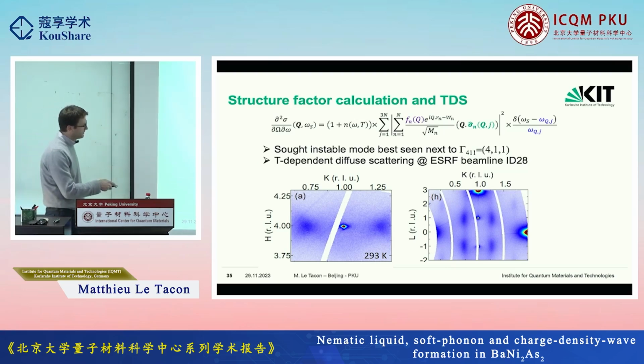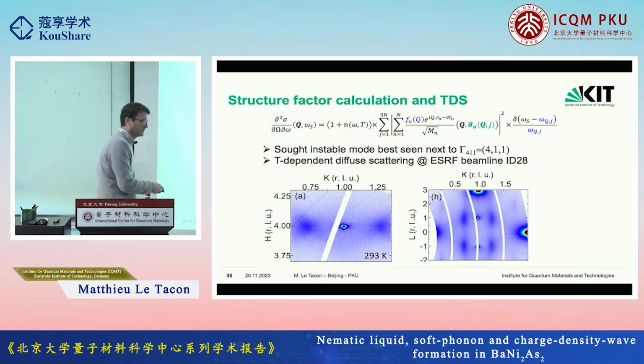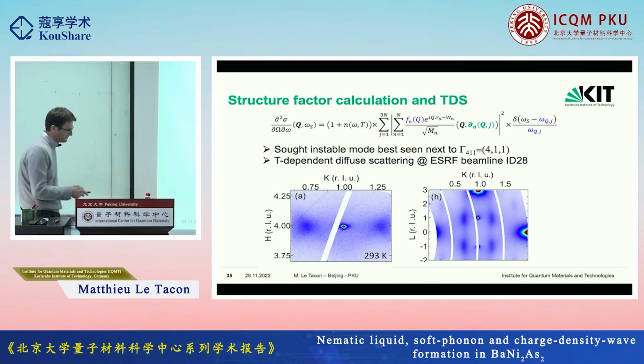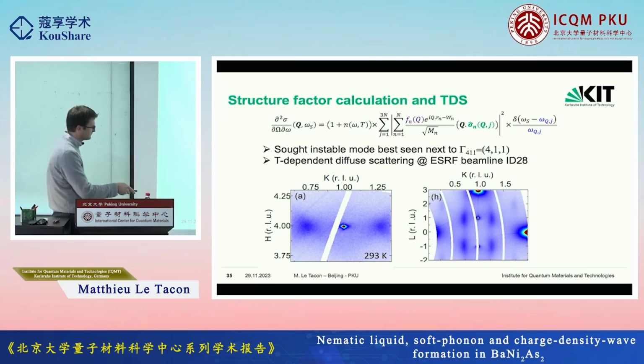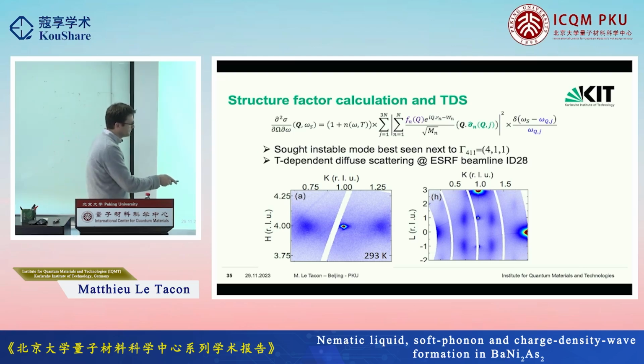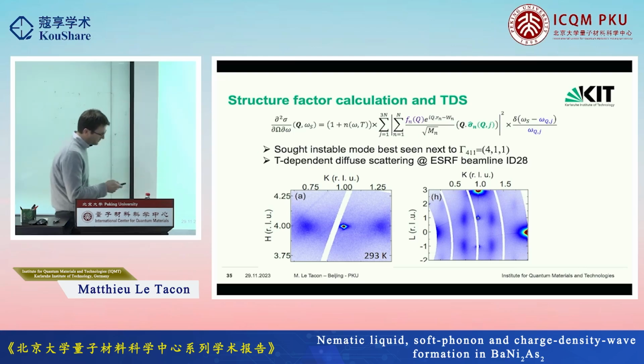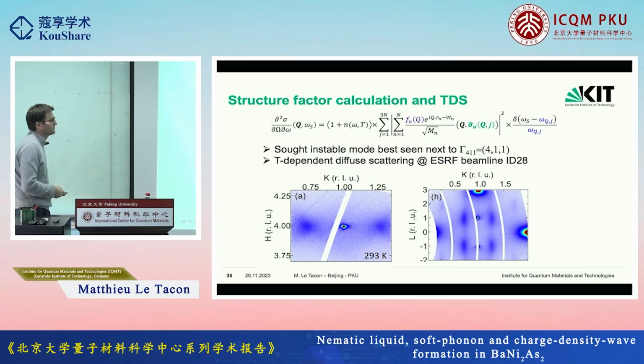Okay, so this is very weak, very diffuse, very broad, but with this kind of machine you can of course see it, and you can see that along the z-axis you have this nice modulation. So this is the HK1 plane, and this is the 4KL plane. Okay, so you see, these correspond to the diffuse scattering associated with the phonon.